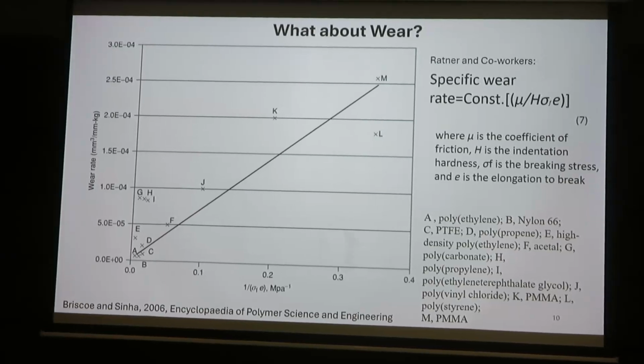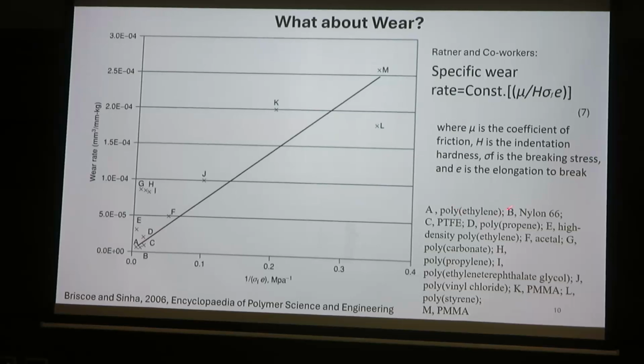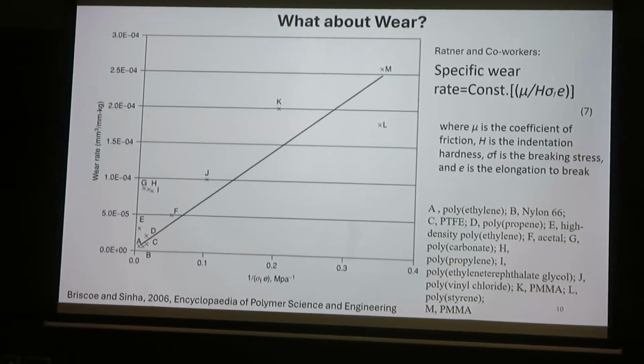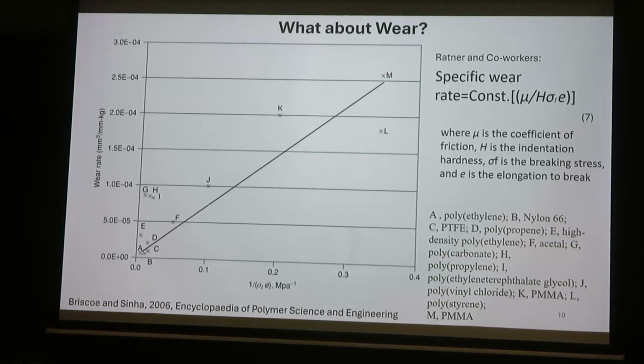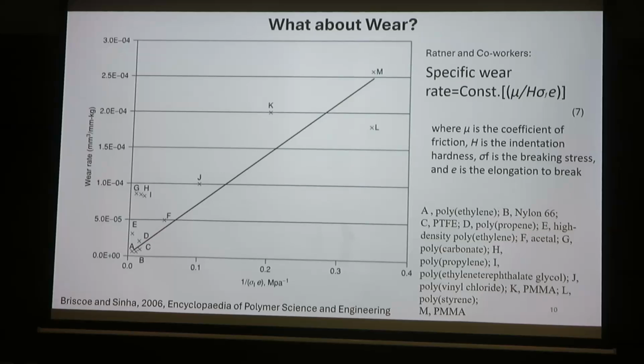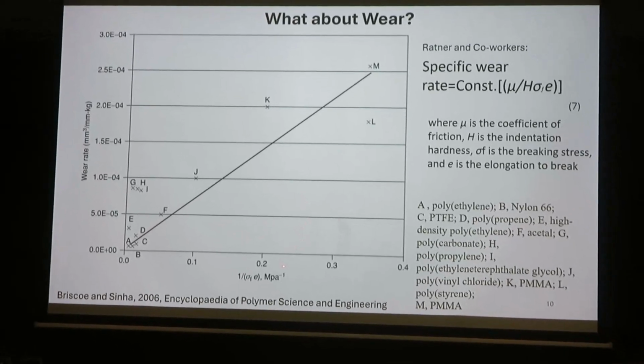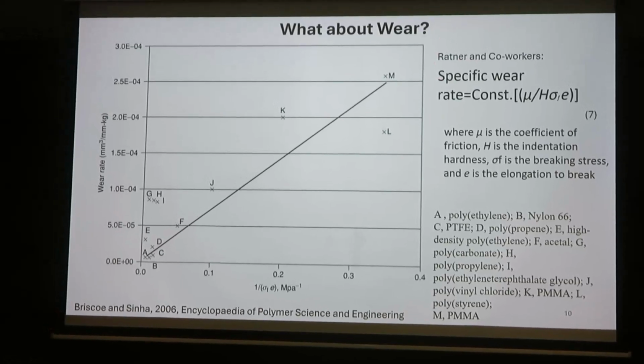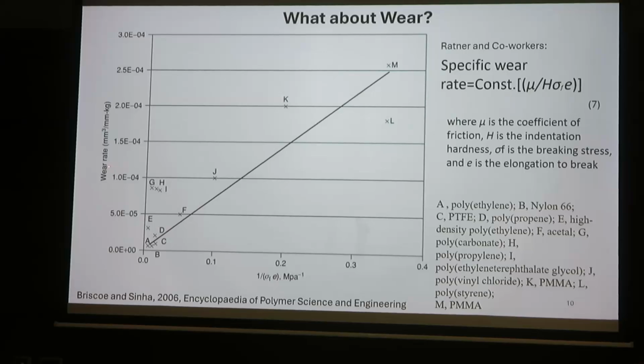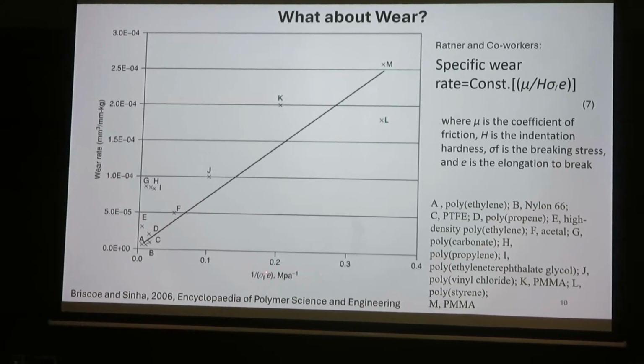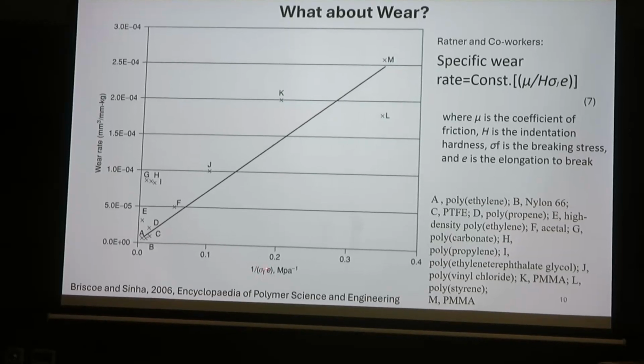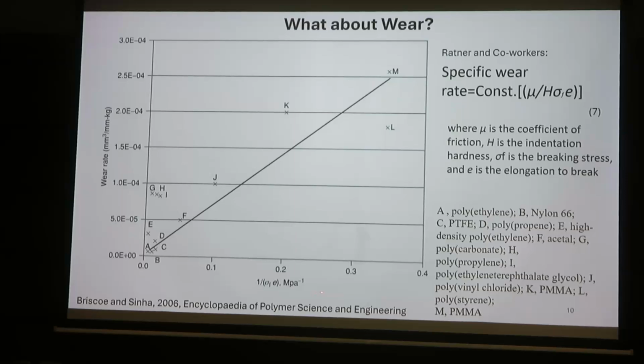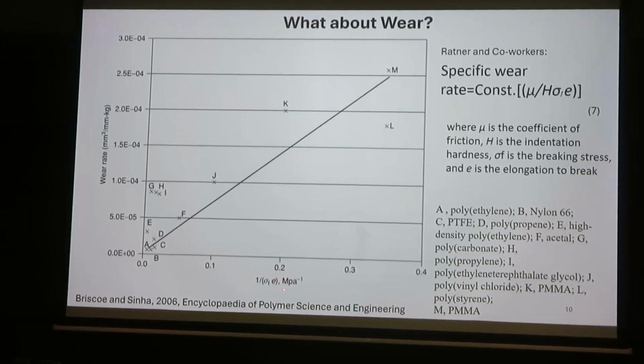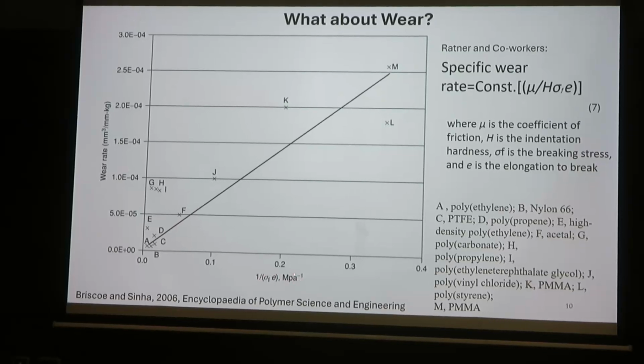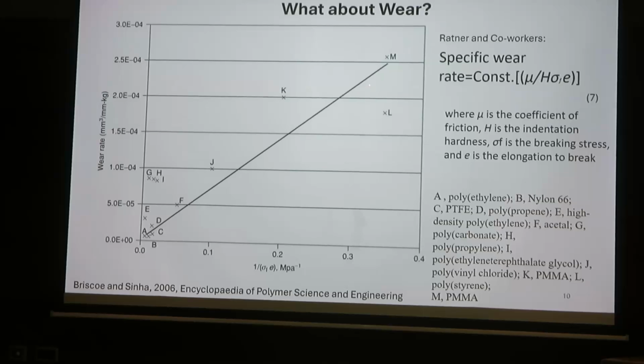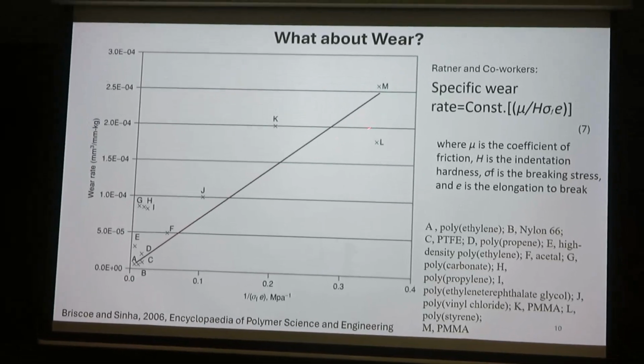So that's about friction. What about wear? Actually, for polymers it is very hard to give any kind of model that can take care of the wear part. But this graph, you will see, has come out from Ratner and others' work, where specific wear rate was related to 1 over sigma F epsilon F, where sigma F is the tensile fracture stress and epsilon F is the elongation at fracture. So in some way it is related to the plastic deformation property of the material. If we plot this, at least for pure polymers, we can see some sort of linear relation.